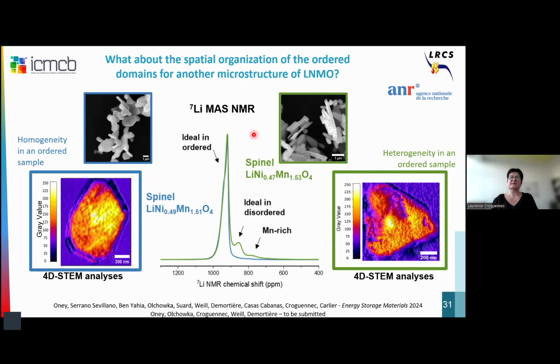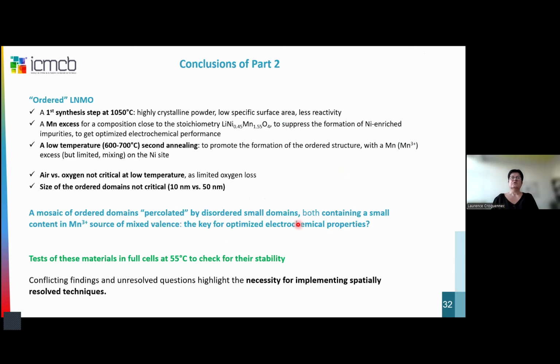And here, for the spinel that already shows defects, ideal for disordered, manganese-rich, we have much more heterogeneity in this particle, with a disordered domain here and an ordered domain here. So just to conclude this part 2, in this material we are not in disordered materials, and they behave very well in a battery in electrochemistry upon long-run cycling at high C rates. But we are in a material with this mosaic effect of ordered domains, percolated by small disordered domains. And we think that both contain manganese 3+, which is the source of mixed valence, and that is the key for optimized electrochemical properties.